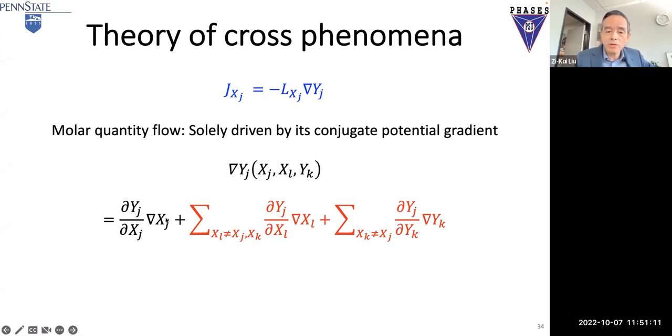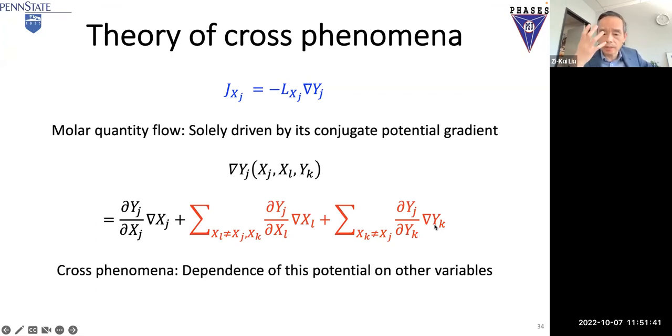But if you take this term only as Fick's law, then Fick's law is inaccurate. Okay, Fick's law is inaccurate. I really think we should not teach Fick's law in our class anymore, because you have other contributions here. Another composition, for example, temperature gradient, or electric field gradient, or magnetic field, right? Or it's a stress, like what we were discussing before the seminar here. So this is a phenomenon, this observation. Observation: temperature can drive diffusion, for example. It's not because you need a temperature gradient here, it's because the chemical potential is a function of temperature.